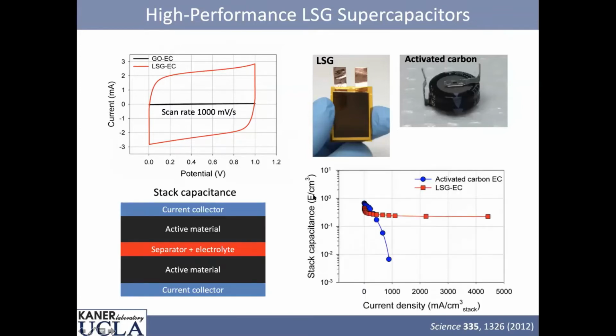This is stack capacitance in farads per cubic centimeter versus current density. This is a commercial device in blue. Our device is about the same. As you run them harder, the commercial device falls off. Ours is still performing above 4,000 milliamps per cubic centimeter. So graphene is a really good material. You can charge it fast. You can discharge it as fast as you like.